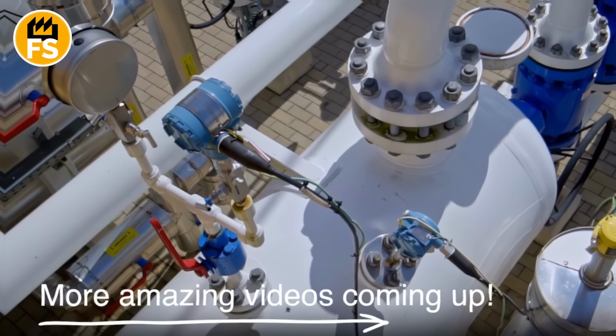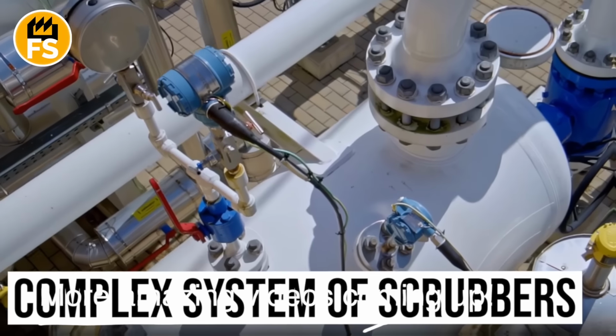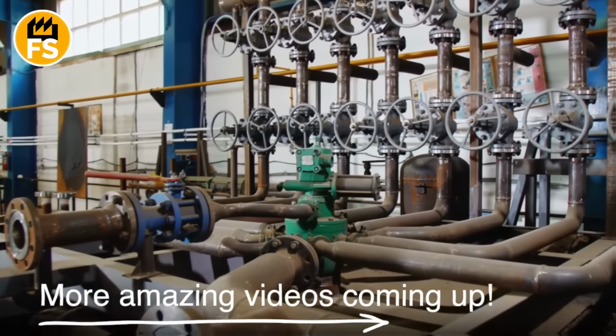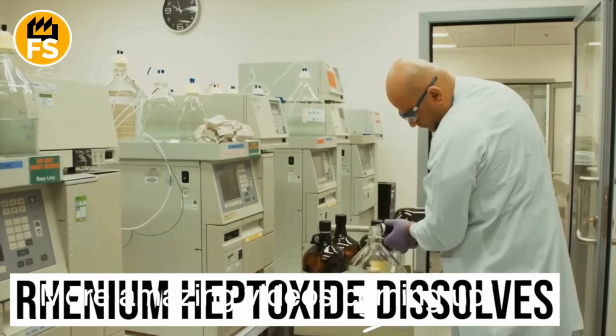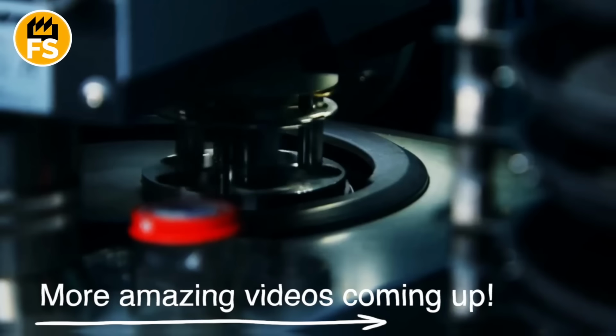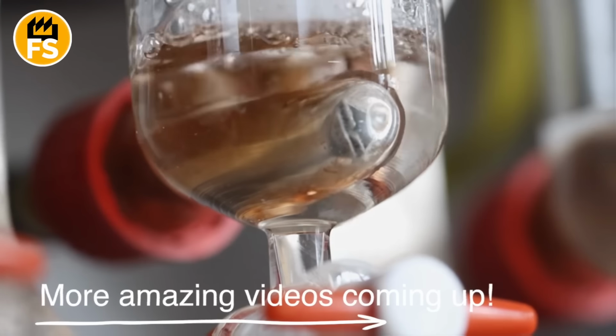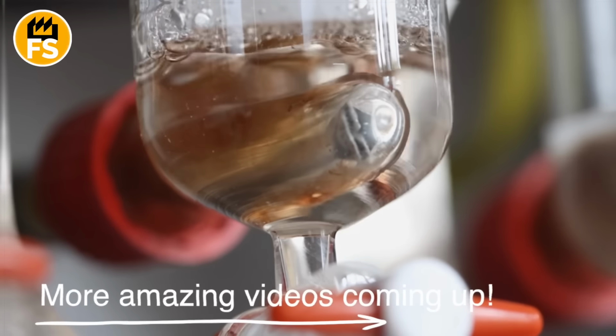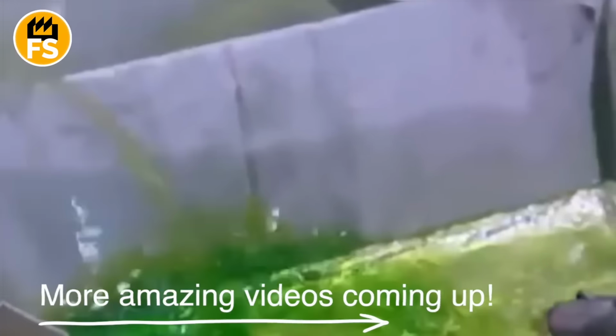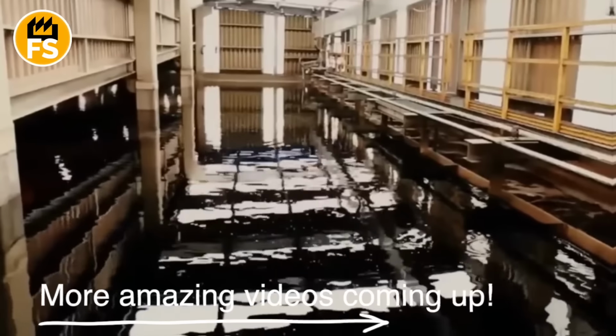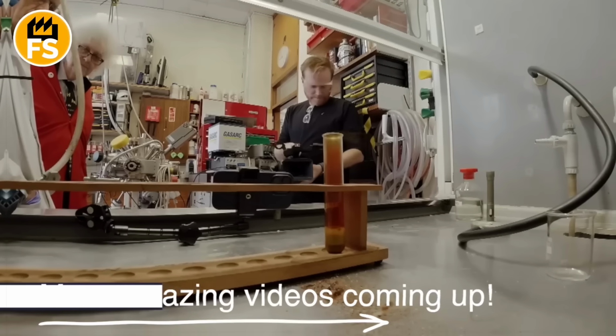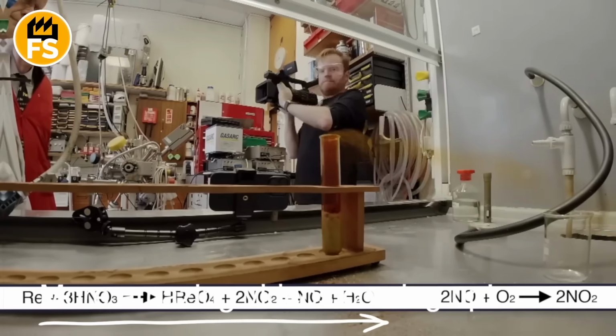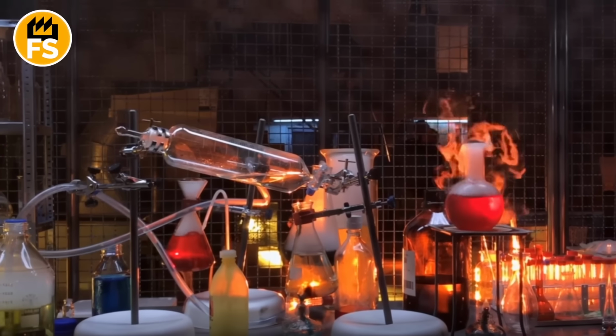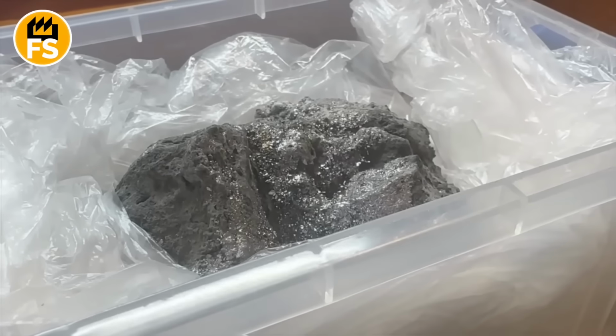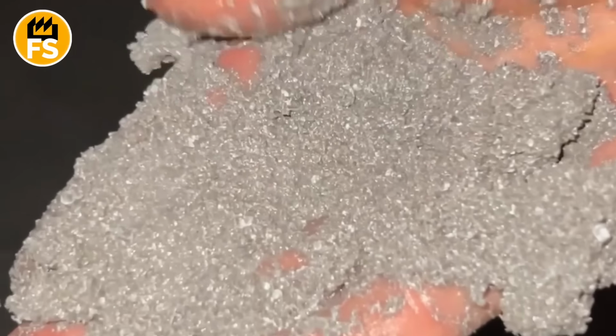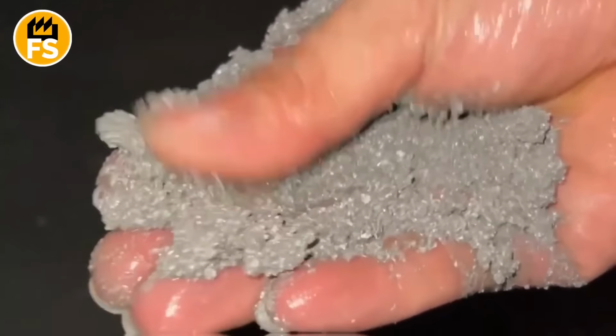The gases pass through a complex system of scrubbers, towers where the gases are washed with water or alkaline solutions. Rhenium heptoxide dissolves, forming rhenic acid or perrhenates. The concentration of rhenium in these solutions is minuscule, grams per ton, but it's something workable. The solution is purified from impurities of molybdenum, copper, lead, and other metals through multi-stage chemical treatment. Then, rhenium is precipitated as a white crystalline powder. This is the most common form of rhenium feedstock for further processing.